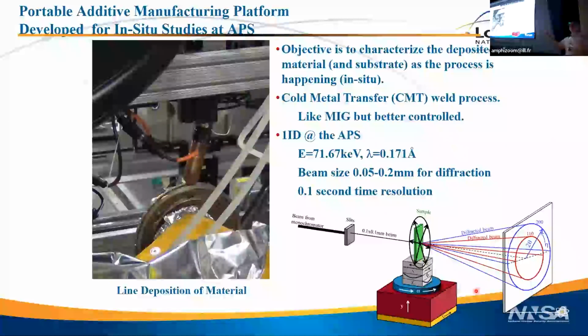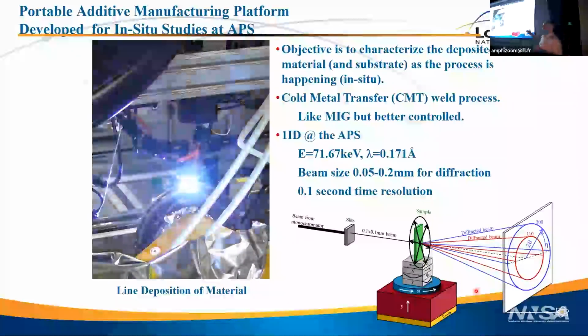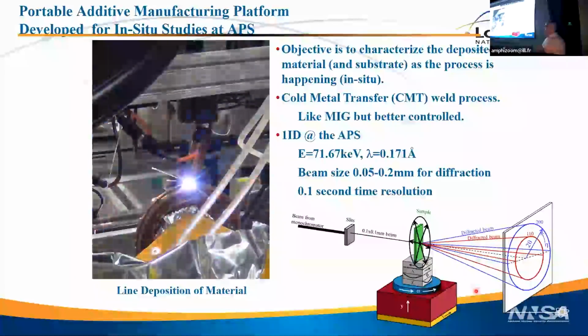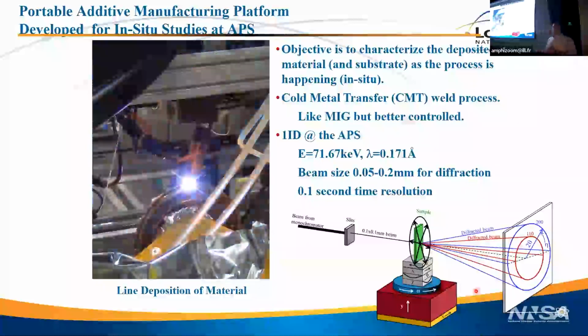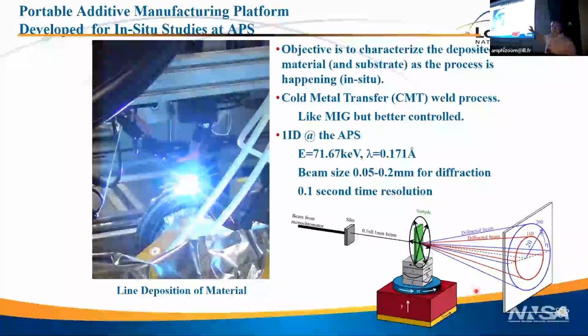I wasn't expecting sound. So this is my first example. We're doing an in-situ additive manufacture. Again, because, first of all, this was in 2017, so the detector was slower. So we did wire arc additive manufacture because we knew the kinetics would be slower. Going into it, we know this is cooling at something like 1,000 degrees per second, not 1,000,000 degrees per second like powder bed fusion. Okay, so again, we tried to pick a problem that would fit the kinetics